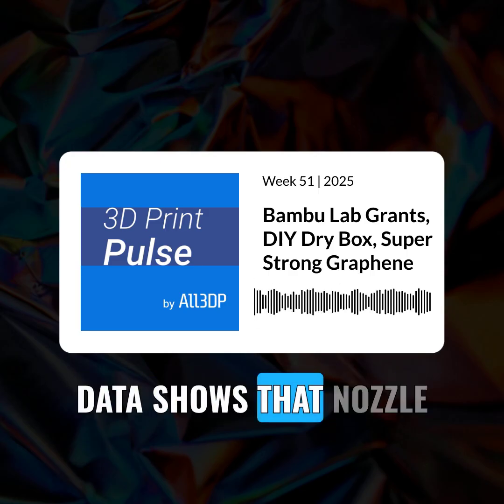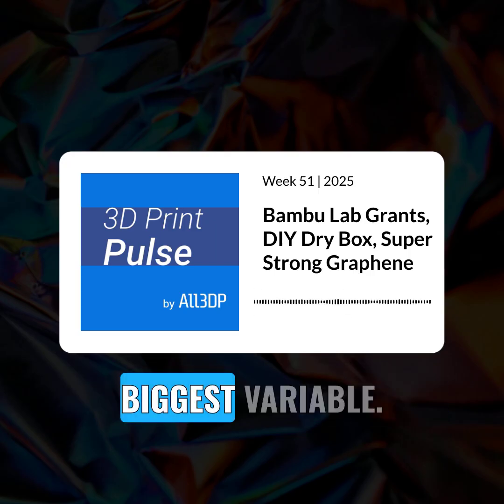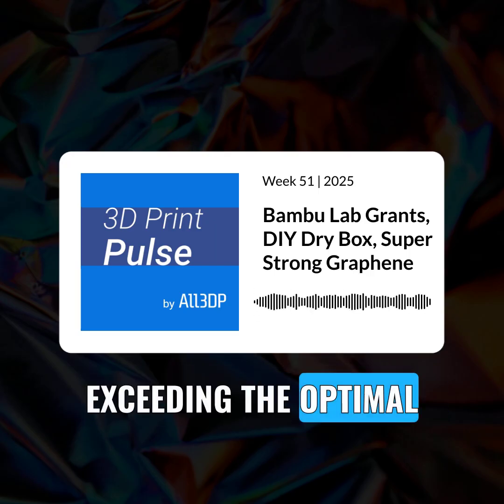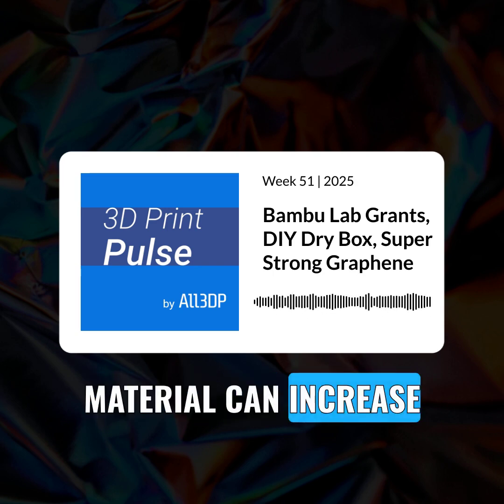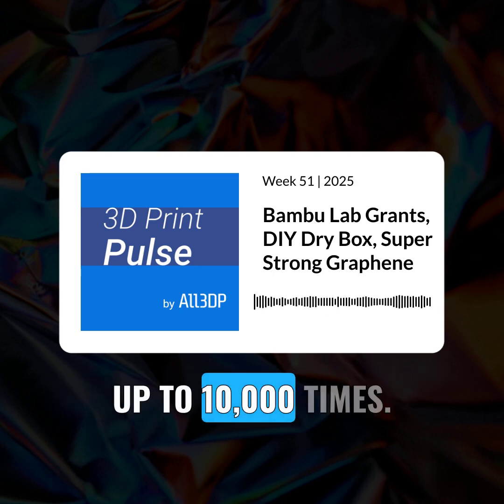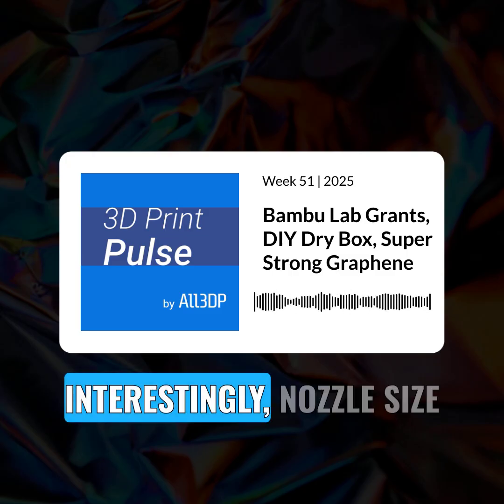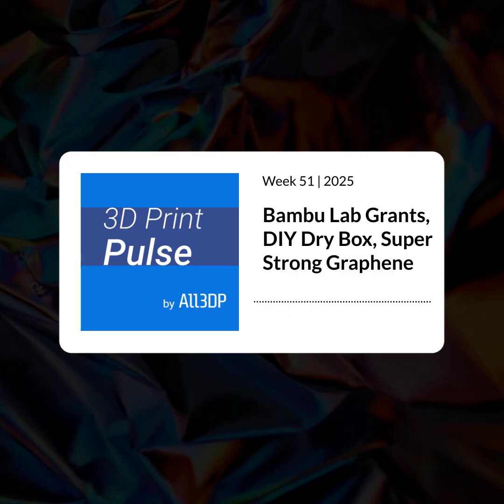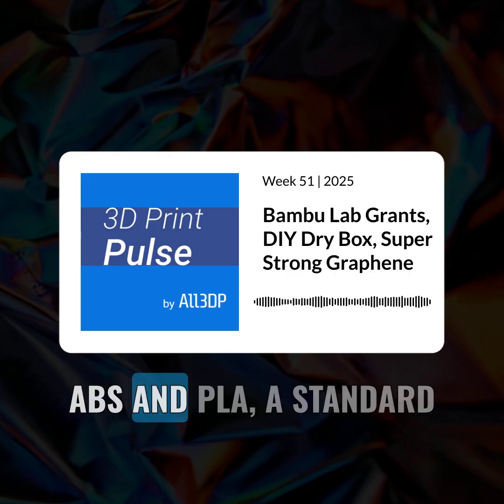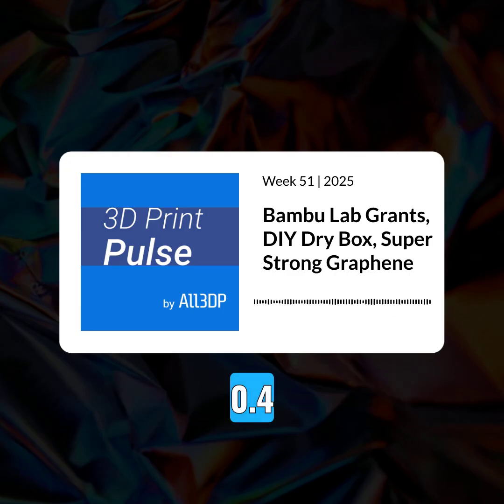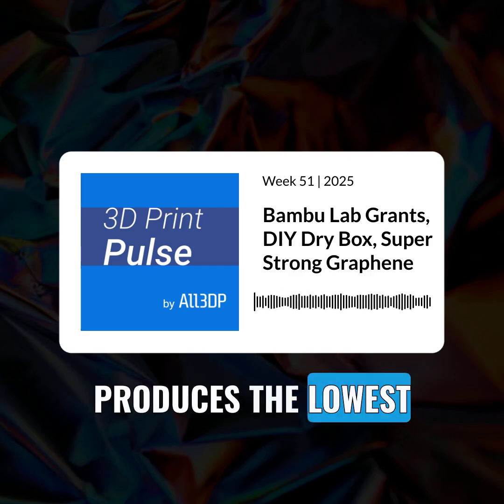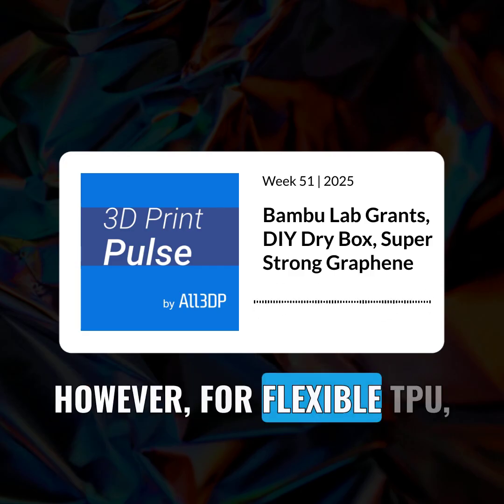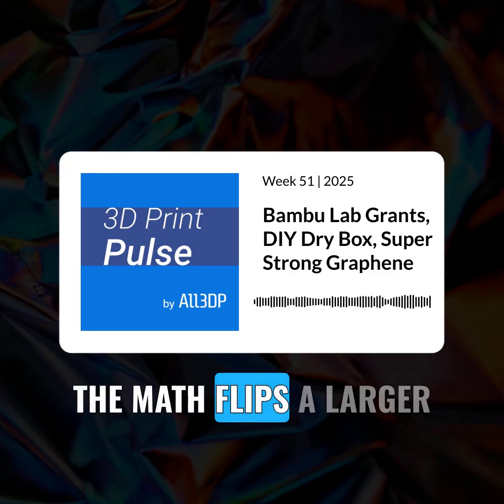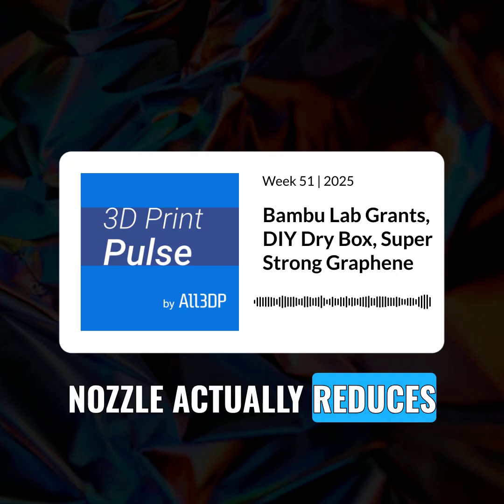Data shows that nozzle temperature is the single biggest variable. Exceeding the optimal temperature for a material can increase particle emission rates by up to 10,000 times. Interestingly, nozzle size matters too. For most materials like ABS and PLA, a standard 0.4 mm nozzle produces the lowest emissions. However, for flexible TPU, the math flips. A larger nozzle actually reduces emissions.